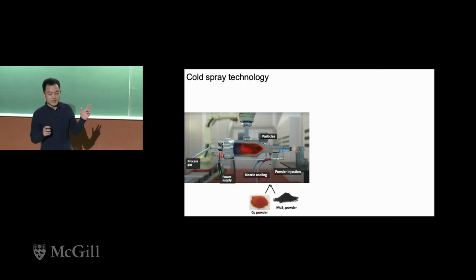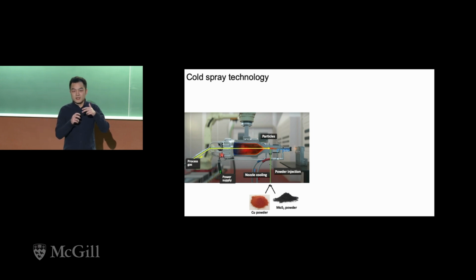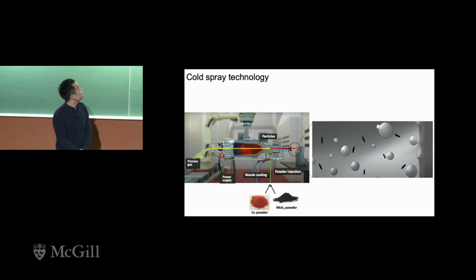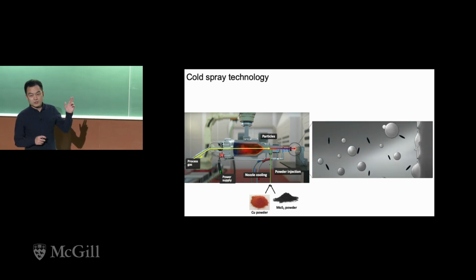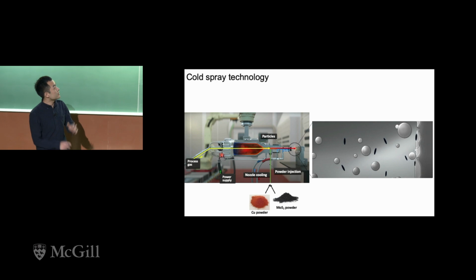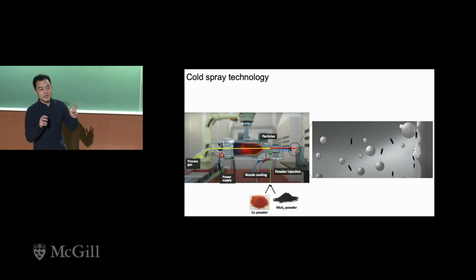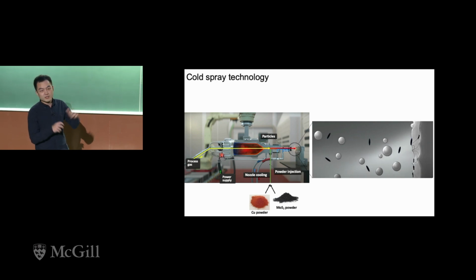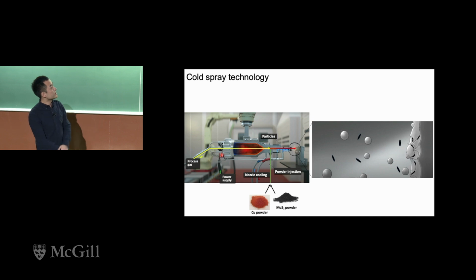The coating is fabricated using cold spray technology, which uses a high-pressure gas to spray the injected copper and MoS2 powders on a substrate, like this. The copper particles shown as gray spheres can bond due to their ductile property, and MoS2 shown as black particles will be entrapped in the coating.